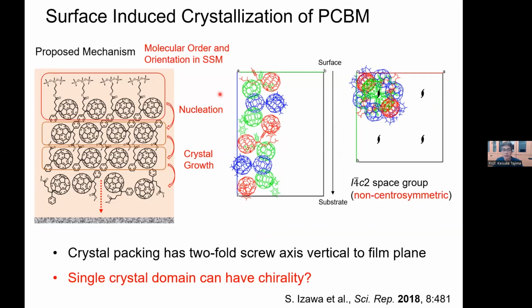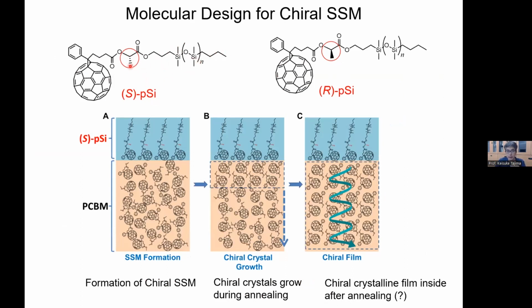If this is induced from the surface, can we imagine controlling the direction of this helix from the surface? PCBM is not chiral, right? So it doesn't have a selectivity for the direction of the helix. But if you induce it somehow from the surface, can we get chiral formation of the helix? So we designed a similar molecule, but with a chiral center in the middle, and the S and R enantiomers were synthesized. What we expect is that, for example, the S version induces crystallization similar to the previous case, but the direction of the helix is determined by the molecule we choose for the surface segregation. So this is what we expected.